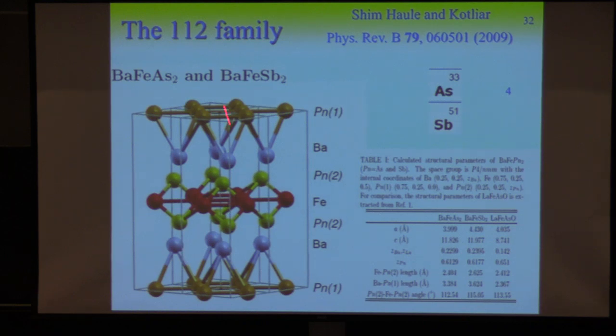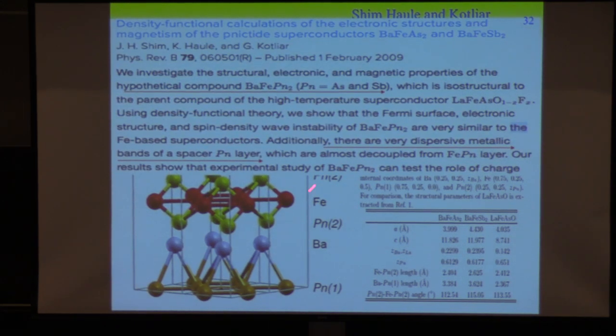And we came across the idea of making a 1-1-2 family. So rather than 1-2-2, which already exist, we started to propose a few compounds and look at their properties. And we noticed something very interesting. We noticed that these are like ordinary iron pnictide superconductors, but the spacer layer is actually metallic. And we were rejected from PRL and forced to write the paper in PRB, and forced to call it a hypothetical compound by the editors because the compound didn't exist.